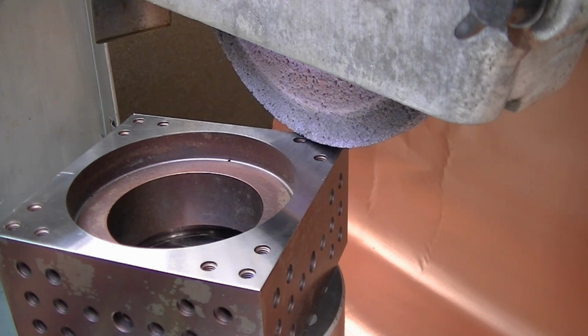Now, there's a lot of things involved in how much cutting pressure there is. The wider the engaged wheel width, the more pressure. So if you're out to get the most accurate results from the grinder, then sometimes narrowing your wheel width for that condition, especially on hard to grind materials, can give you more accurate results. But then you have the situation where that narrow wheel width is also going to wear faster. So now you have to consider wheel wear in the traverse of the parts depending on how much surface area you're grinding. So it's always a catch-22 on what works there.